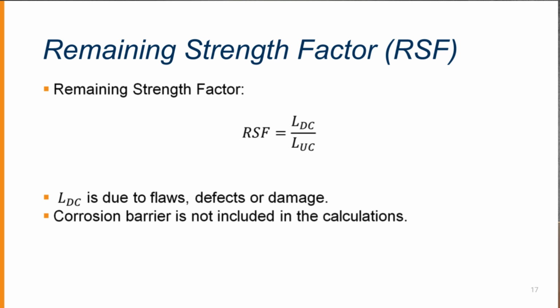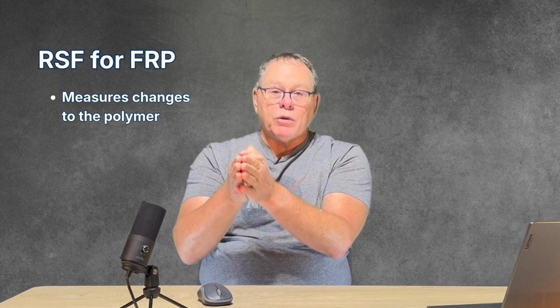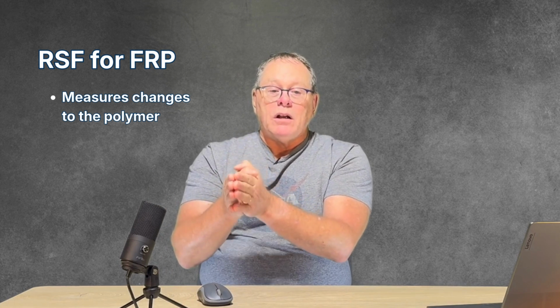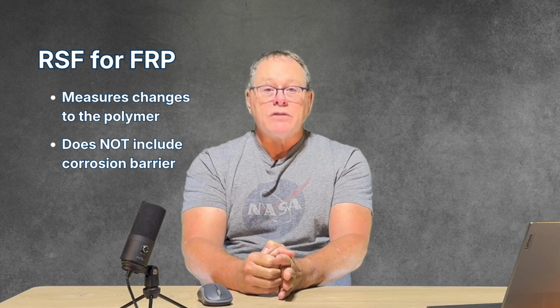We do this mathematically using what's called the remaining strength factor. And that is essentially a ratio of how strong it is now with damage compared to how strong it was when it was new. And we use only the polymer when we calculate that. We know we can't measure what changes have occurred to the glass fibers. So we only measure what happened to the polymer, and we do that based on the polymer. The corrosion barrier is not included in these calculations. Again, we're staying consistent with construction code practices around the world.